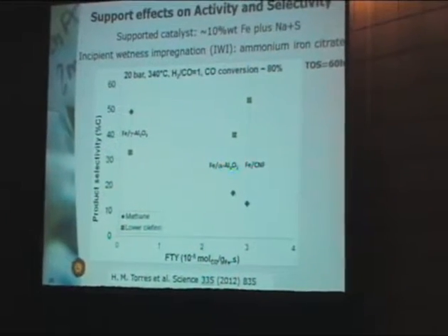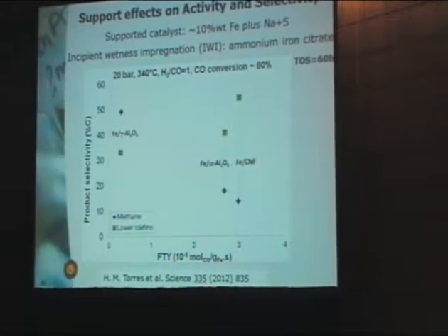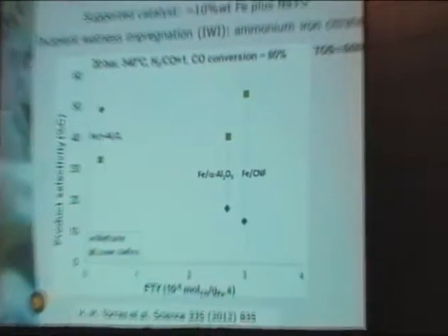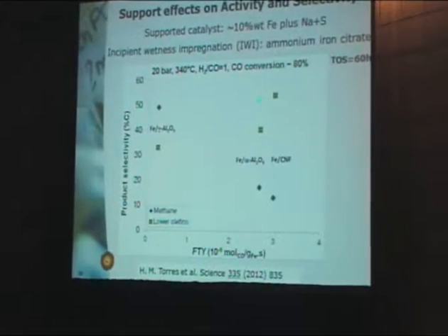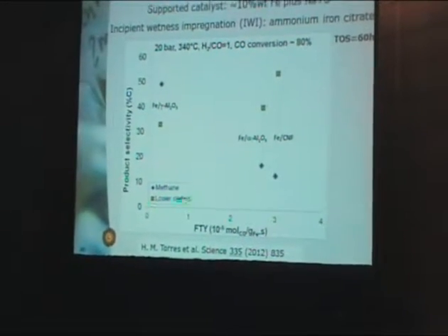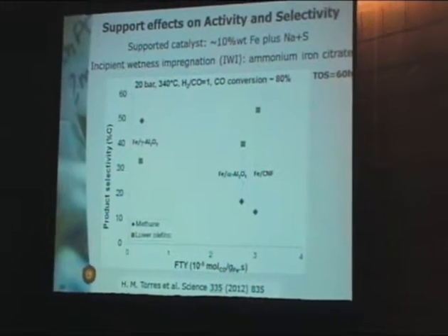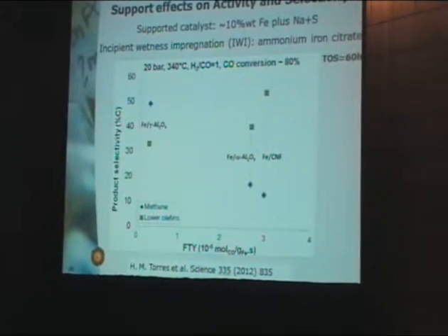Moving to a support like alpha alumina, carbon nanofibers, carbon nanotubes, as has been published recently by Martin Muller and his group, gives much more active catalysts, but also drives down the methane and enhances the green points, which are the selectivity to lower olefins of the hydrocarbons produced.